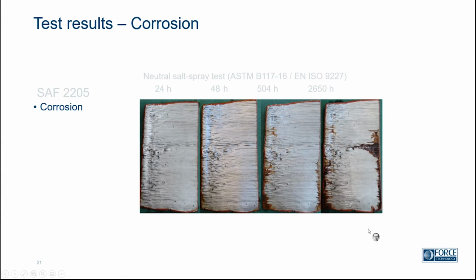And this last one is just to show that it's also important to know what you're looking at, because here we have a duplex plate geometry printed and exposed to neutral salt spray for various numbers of hours. It's the same panel carried through all of them, and we see some corrosion in the beginning, around 504 hours, and it appears to have developed when we reach 2650 hours.